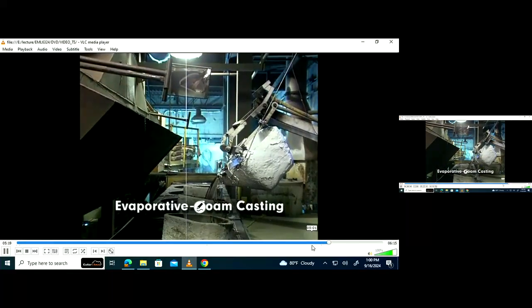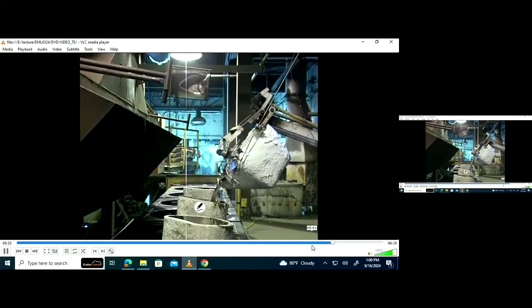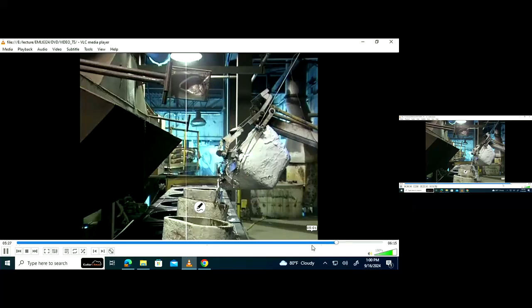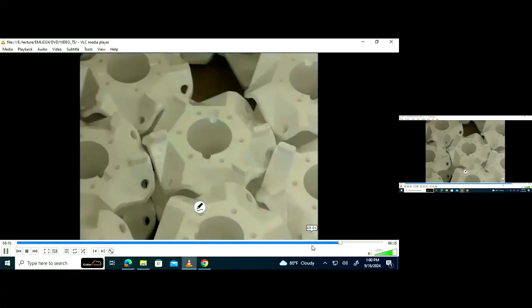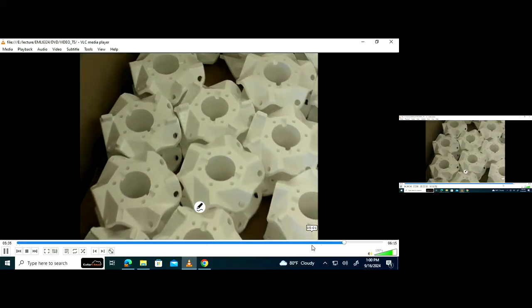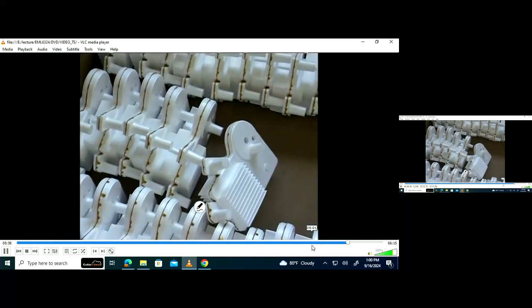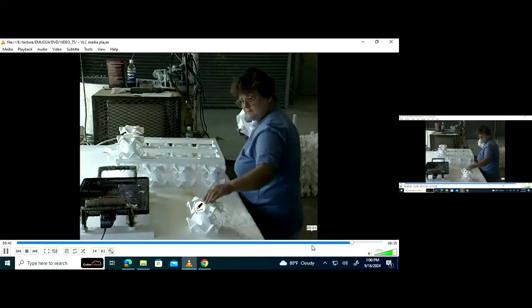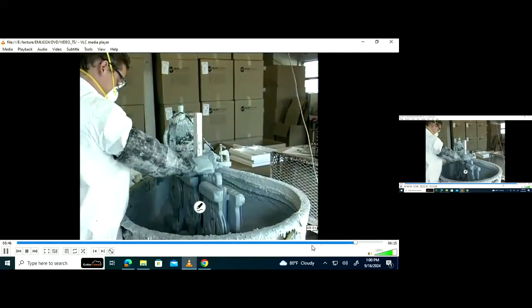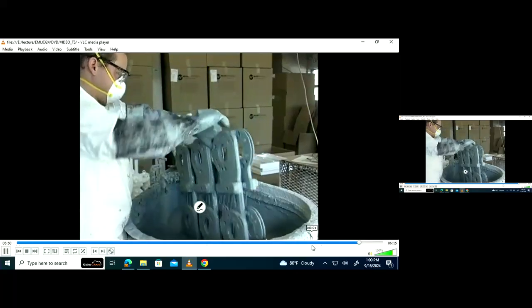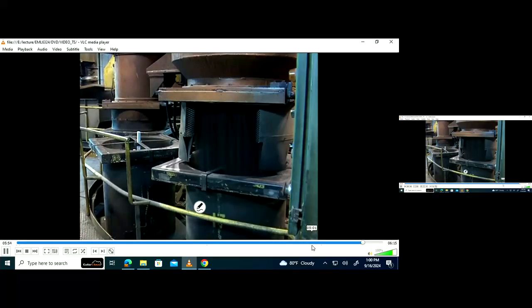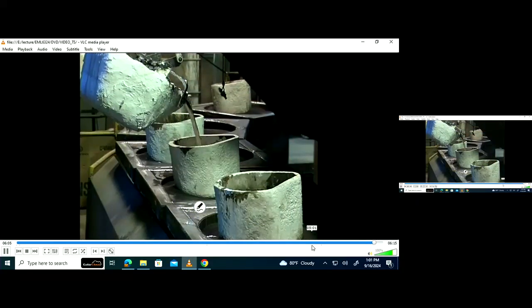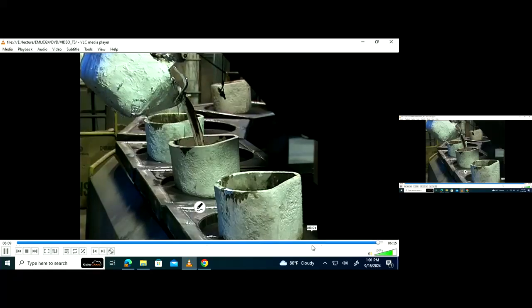Evaporative foam casting refers to the use of expendable polystyrene foam patterns in molds made of dry, unbonded sand. The process is also known as the lost foam or expanded polystyrene process. The pattern may be a single piece, or for complex shapes, an assembly of molded pieces. Patterns also can be clustered in groups to produce multiple parts at a time. The pattern is coated with a thin, high heat-resistant coating, usually silica. Once the coating is dry, the pattern is placed in a flask and surrounded by sand, which is vibrated for compaction against the pattern. Casting then proceeds with the poured metal evaporating the polystyrene foam and filling the cavity formed by the pattern.